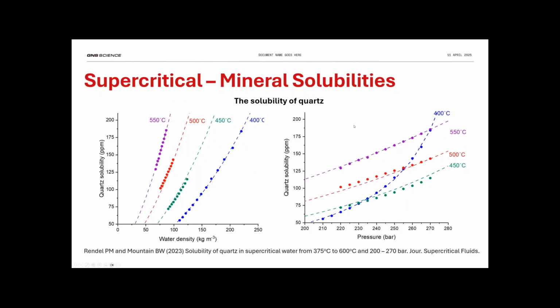So this is an example of some of the work that we've done. This was published in 2023 in the Journal of Supercritical Fluids. This is the solubility of quartz from 375 to 600 degrees and 270 bars. And you can see these beautiful solubility data along the isotherms. Each dot represents 20 measurements, and they're separated by 5 bars. So we're able to distinguish the change in solubility at 5-bar increments at these extreme temperatures.